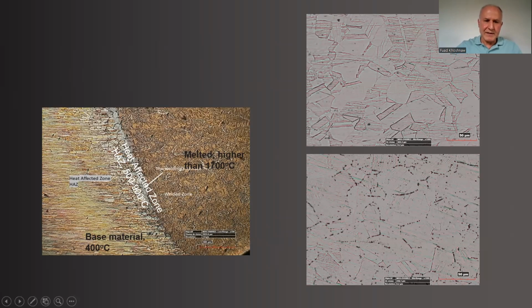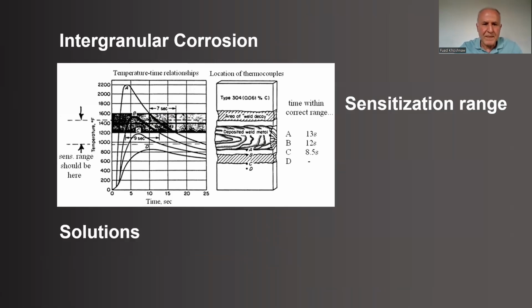corrosion. That somehow happens in the heat affected zone in the welding area, because this is molten, and this is base material, but the heat affected zone passes through this sensitization range, and this chromium carbide forms. So this is before, this is after, on the grain boundaries. And because of this, it is not as before, the chromium has been depleted, so when this is exposed to any solution, these areas will be more susceptible to pitting or general corrosion.